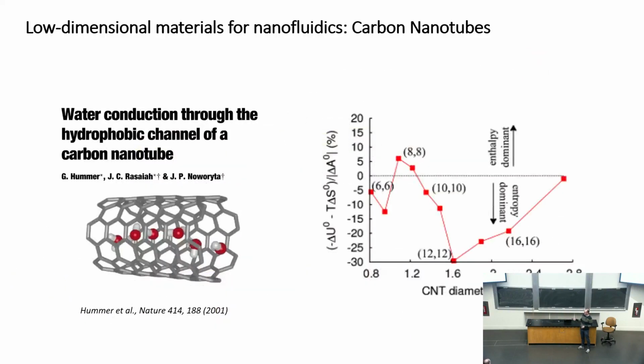And it was only 10 years after the initial discovery of CNTs that an MD simulation really made a big impact in this field, where Hummer and coworkers looked at this very small pore, like the one that I showed you in the beginning, and they put water in, and they saw it forms this single file chain you never see in bulk water ever. And they suggested this would have very different properties than bulk water in terms of transport rates. They predicted correlated movements, this very fast, rapid burst-like motion in this CNT. And this sparked a lot of interest, and finally experiments were able to show it actually does fill with water.